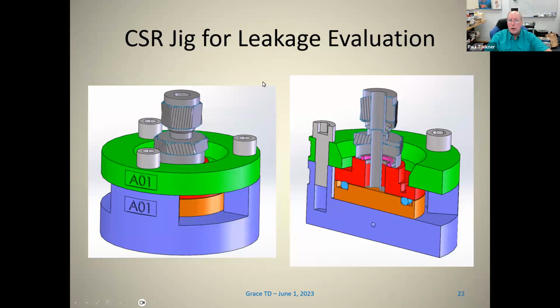Another thing you can do is use a jig I designed for oil and gas that has a special shim on top allowing you to put a Swagelok fitting in there for leakage testing. So you can do CSR testing and measure the sealing force, then at intervals check it for leakage, or do both at the same time if you have the right configuration, like I showed earlier.